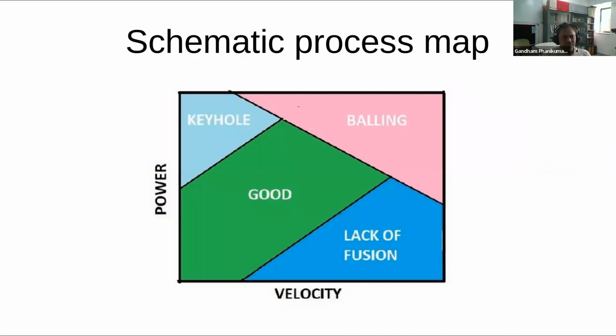And so lack of fusion and keyhole both will give you porosity, but they're actually on different sides of the power spectrum. So you have very high power, you get keyhole porosity. You have low power, so low that the velocity is too fast and doesn't allow the powder to fully melt. Then you have this problem of lack of fusion, giving you some amount of porosity.